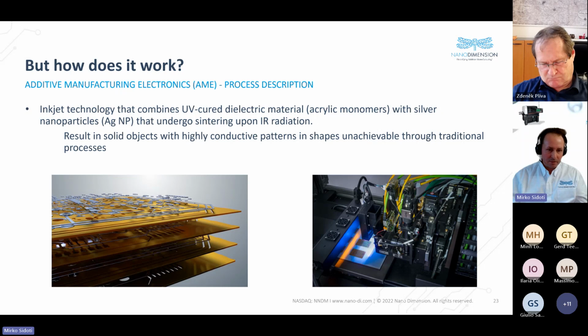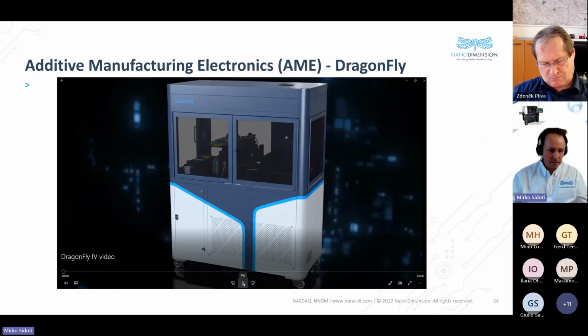Both the materials, the inks, are jetted. And so basically what we print are droplets. We are jetting droplets of 36 micron of diameter. And each layer we cure and sinter the 2 inks, using the UV to cure the dielectric, and infrared radiation to sinter and dry the conductive ink. So after sintering and curing, we have solid layers overlapped one after the other, resulting in a solid 3D structure.